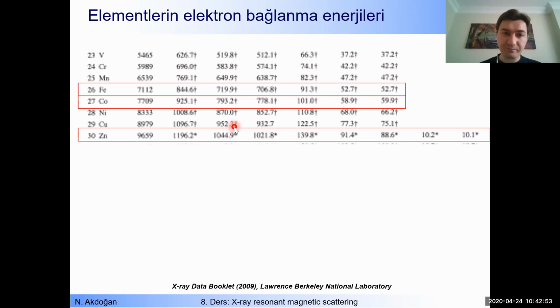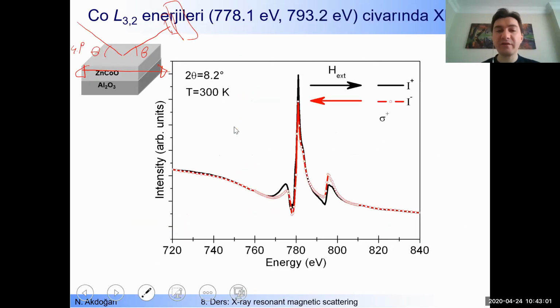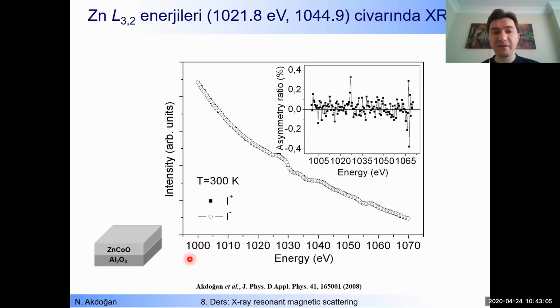Hopefully at that time, the energy range of the beamline was okay for us. Then we also investigated the zinc edges. So here you see starting from 1000 electron volt to 1070 electron volt. What do you see here? I plus, I minus. We apply magnetic field and record intensity as a function of energy, and reverse the direction of the magnetic field and record intensity again. The resolution of the signal is very low because we are almost at the limits of the beamline energy range. And what else? If we plot the asymmetry ratio for both signals, what do you see? Zero. There is no signal from the zinc, and it is expected.